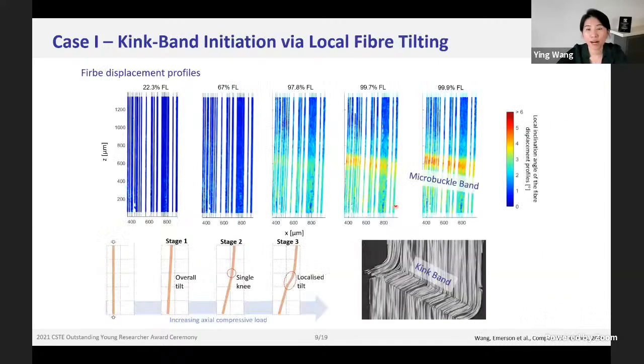But it's amazing to find that if we look at the fiber displacement profiles, which is the deformed fiber profile deducted by the initial fiber profile, we clearly see a trend, which is really not so visible to human eyes, but we can quantify the fiber tracks and get the values out of the fiber tracks. And we can see a localized region with higher tilting angle in the displacement profile.